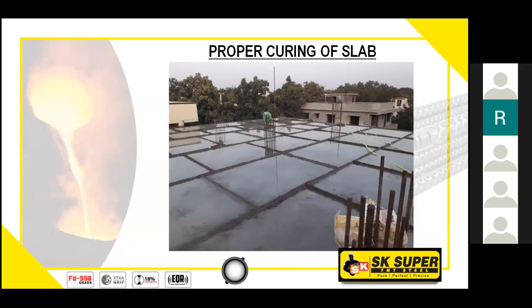I'll just share one small example with you what I have gone through. When 53 grade was launched, we used to get complaints, sir, the plaster is cracking and the slabs are cracking. It was only small hairline cracks. But as 53 grade has more heat in it, the hydration process will be more. Now, what is an ideal thing to do? Suppose you are casting a slab of 1,000 square feet. Once you cast one portion of 10 feet by 10 feet and you go to the next portion, immediately start to sprinkle water on the portion which has been casted.